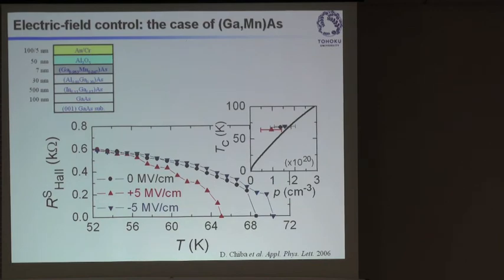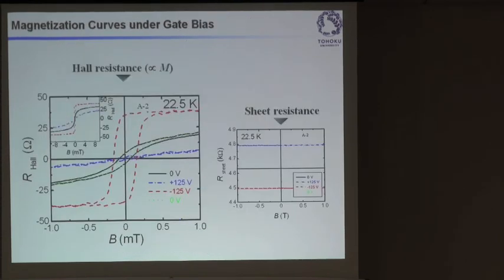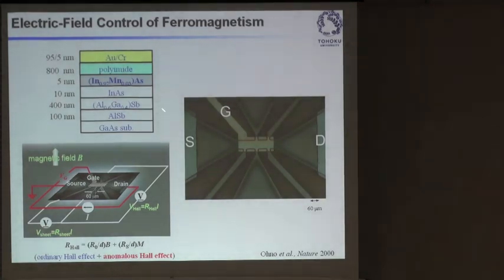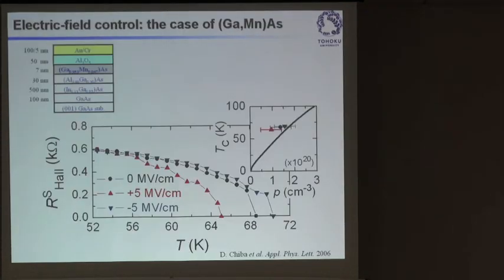This was done in indium manganese arsenide. We can also do the same thing in gallium manganese arsenide, although it took us some time to develop the technology. So basically, this is the same thing, but instead of indium manganese arsenide, we have gallium manganese arsenide. And we apply an electric field to change the transition temperature. This is, again, the spontaneous magnetization measured by the Hall effect.